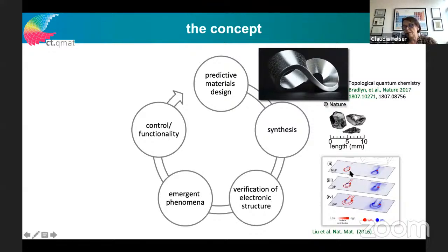The best ways to do this are photo emission or STM investigation. So you can see here the calculated surface states, for example, from some Weyl semi-metals. I'll explain soon what a Weyl semi-metal is. And this is ARPES, the angular resolved photo emission data, which shows a very nice agreement.